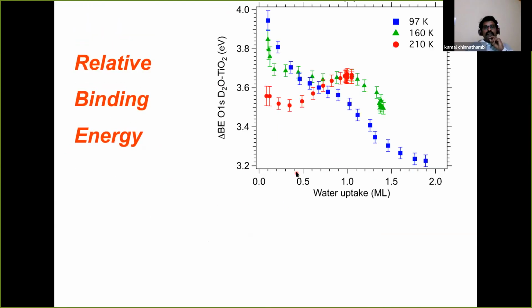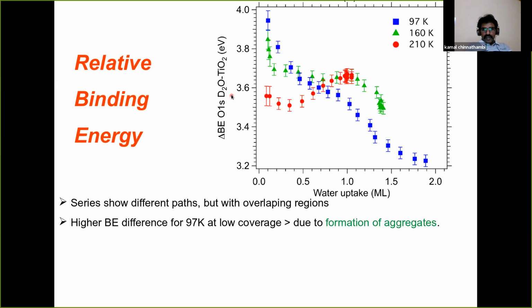But the most important result from the experiment is this slide. This slide contains the binding energy information. Instead of working with the absolute number, they take the difference between the oxygen from the titanium oxide and the water molecules. You can see that these three temperature traces follow different paths, with some overlapping region. The first one, at the lowest temperature, 97 Kelvin, starts from a very high value for the binding energy difference, and then it monotonically keeps going down.